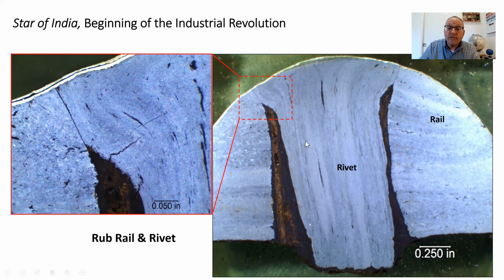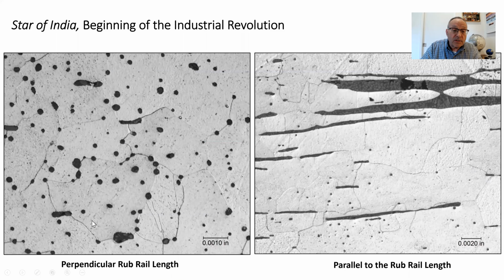If we look at higher magnifications of it, what we see is, and this is perpendicular to the rub rail, and these lines here are the crystal structure boundaries of one crystal of iron and another crystal of iron and another crystal of iron. And you'll see these non-metallic inclusions along the boundaries of those crystals. If you look at it parallel to the rub rail, you'll see again, here's the crystals and here's those stringers all stretched out in the direction in which it was forged. So it was forged in this direction.